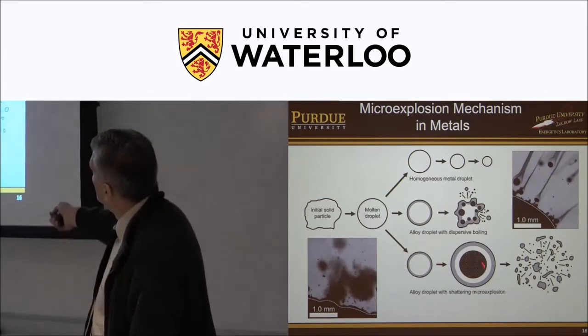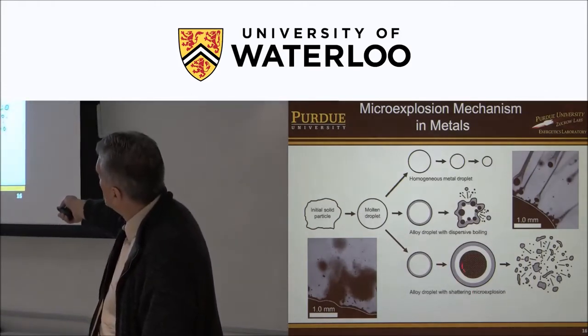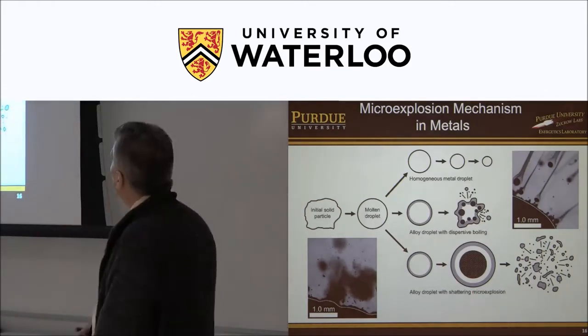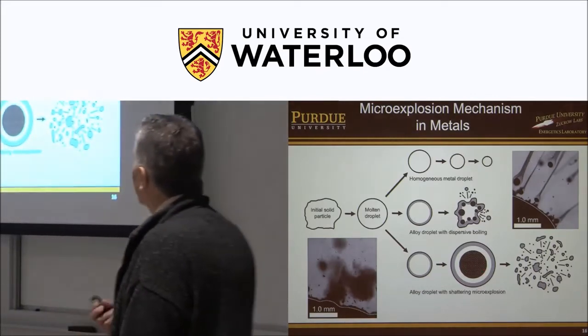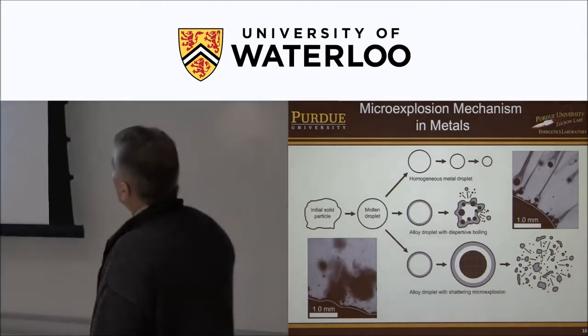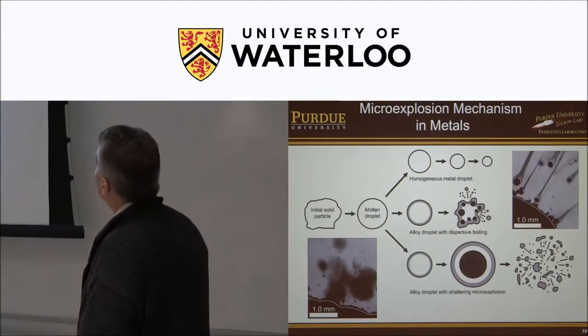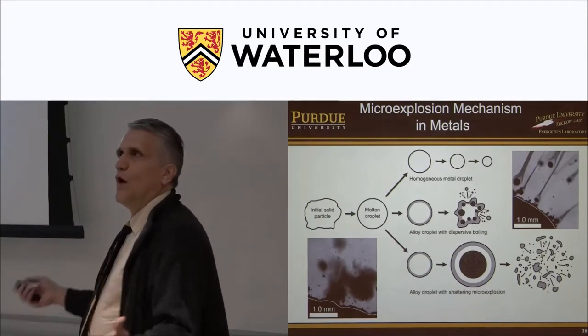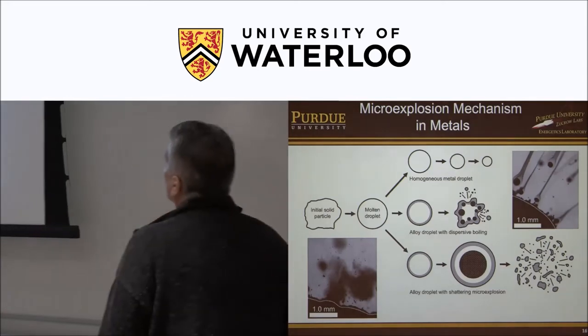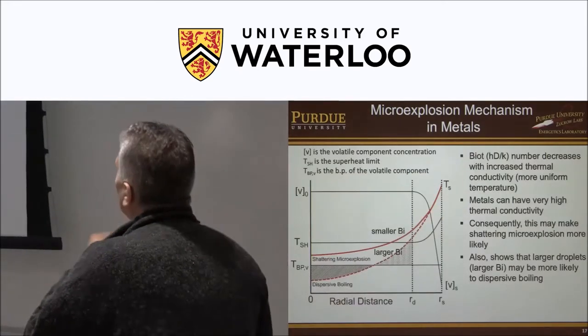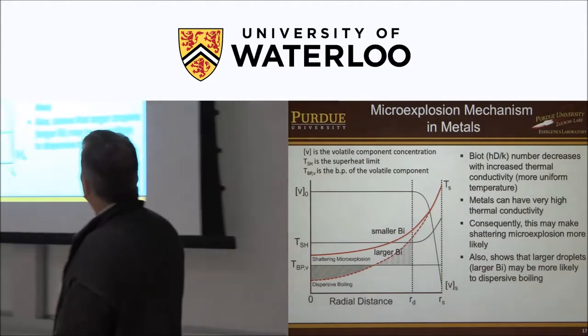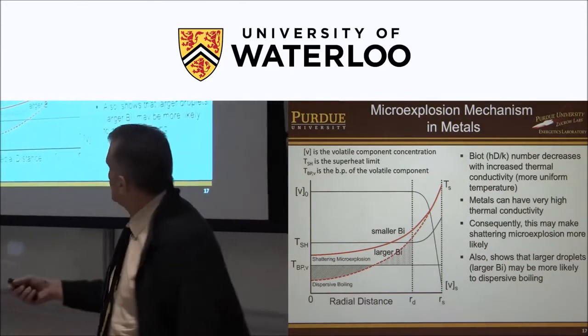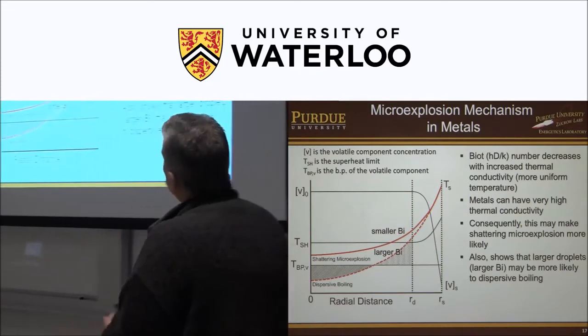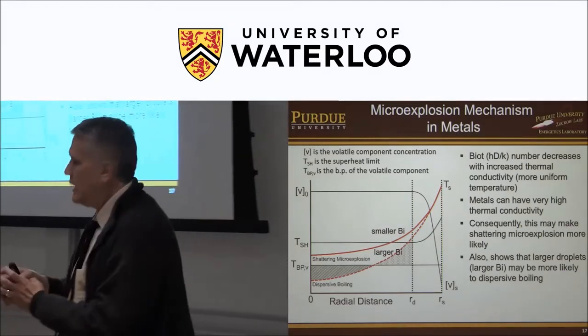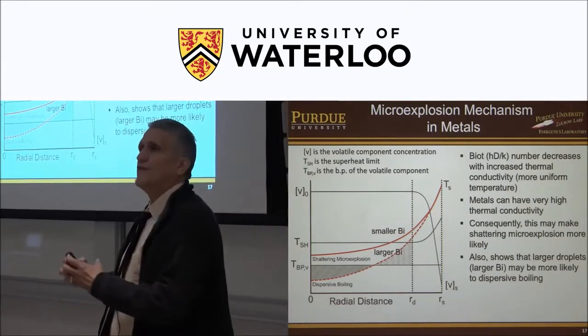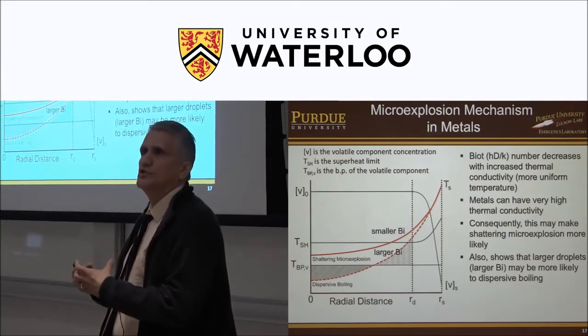Or you get cases where the entire core of that droplet flashes to gas, and we call that a shattering microexplosion, and we saw evidence of that. So why the different phenomena, and what's going on here? So this graph helps us kind of visualize what's happening. And in short, what you have is as you heat the droplet, the more volatile component, in this case lithium, can become superheated.